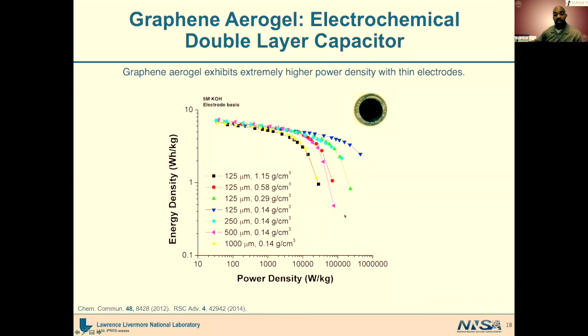If you have a fairly thin electrode, you're able to charge and discharge it up to very, very fast rates without having a large fall off or drop off in terms of the amount of energy that's stored. However, if you go to a very thick electrode, in this case on the order of about a millimeter, you very quickly will see that as you go to faster and faster scan rates, you have this very quick drop off in terms of your performance.